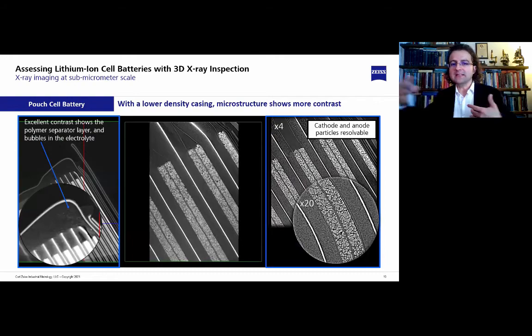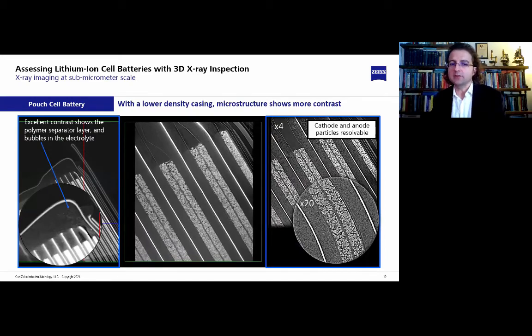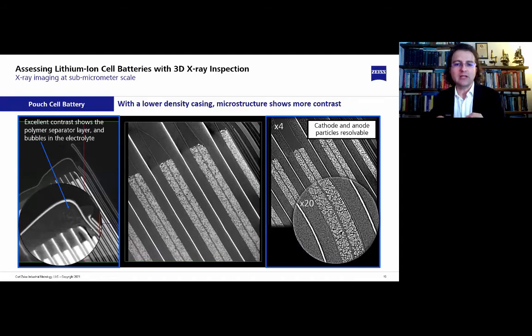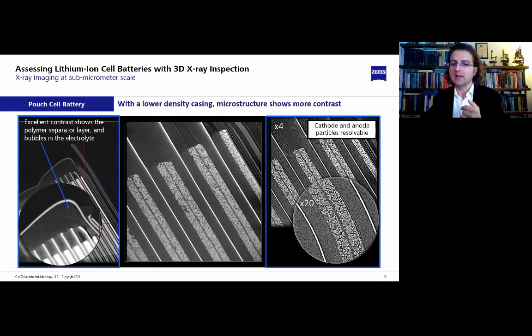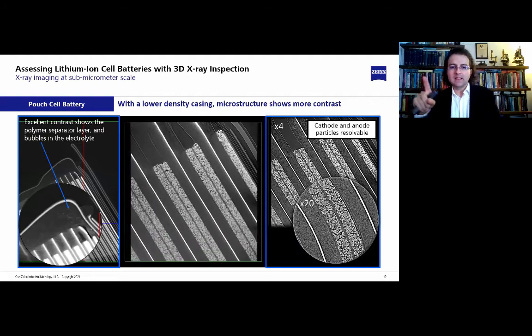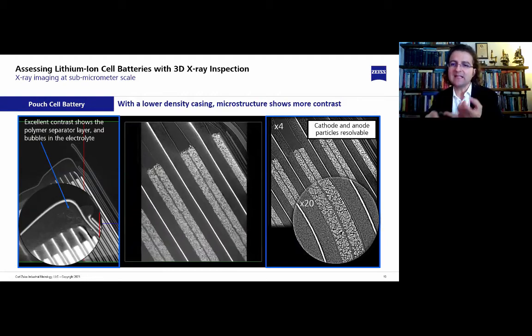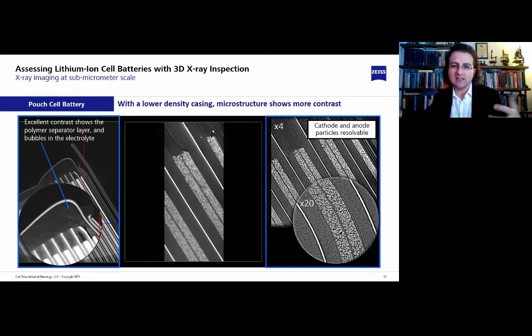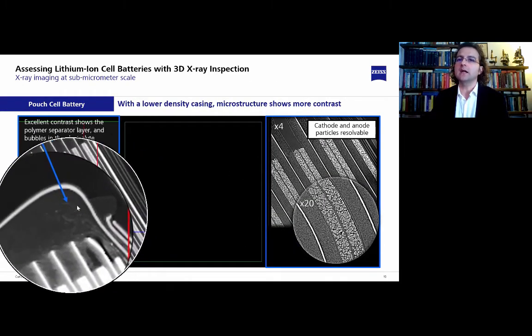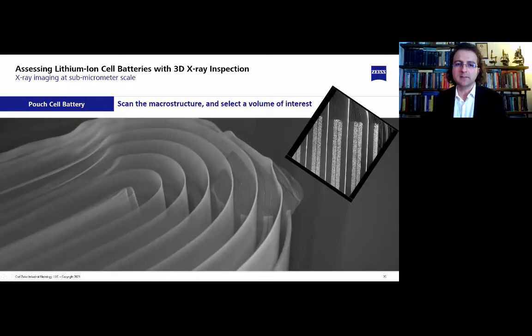And here you can see more details with the X-ray microscopes. Spatial resolutions and voxel size of less than 1 micrometer can be obtained. The image and the video show an exemplary analysis of the internal microstructure of the battery cell, where the cathode and anode particles are resolvable. And the high contrast capabilities of our X-ray imaging tools are even able to reveal low density details, such as the polymer separator layers and bubbles in the electrolyte. I think you can see them here. If not, then I might have a different image in the next slide.